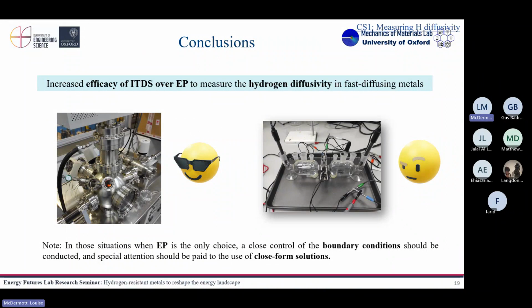That was the main conclusion we got here: with this technique, which of course relies on a piece of equipment that costs about 100,000 pounds, sorry, you can have way better results than if you just use permeation. That said, I think you can get it on AliExpress for less than 200 pounds, so I could do the experiment at home, basically. But that's my takeaway. Of course, I'm going to be using TDS. But we need to be very careful if we use electropermeation to be sure of the boundary conditions we are using. That's something people are usually careless about when they calculate hydrogen diffusivities in papers. So that was our takeaway for this paper.